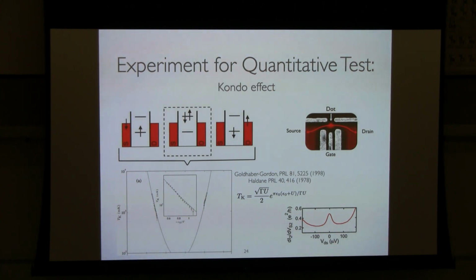Fermi level. So this scaling theory just sat there for quite a while, because if you have one atom of iron, let's say a part per million of iron in copper, you can make a chunk of copper with a tiny sprinkling of iron, you can't adjust just the tunneling rate. You can't adjust just the depth of the level below the Fermi level. You could replace the iron with cobalt, or you could put pressure on and change a number of things at the same time, but you can't really fine-tune one of these parameters. But here in this model system, we can tune each of those parameters and we can measure those parameters precisely.